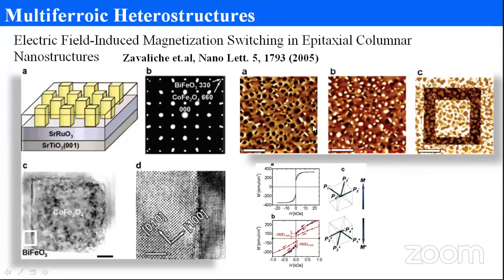Okay, so this is the MFM image where, before polarization, you can see all the magnetic domains are pointing in one direction, and then after applying an electric field, you can switch the magnetization to the other direction. The black dots here change to white on this side. So that shows that in this bismuth ferrite, cobalt ferrite nanocomposite, you can switch the magnetic polarization by electrical polarization. And this is the piezo force microscopy image, which also tells that it is ferroelectric, it has ferroelectric polarization. Okay, so I'm going to explore these bismuth ferrite, cobalt ferrite composites.